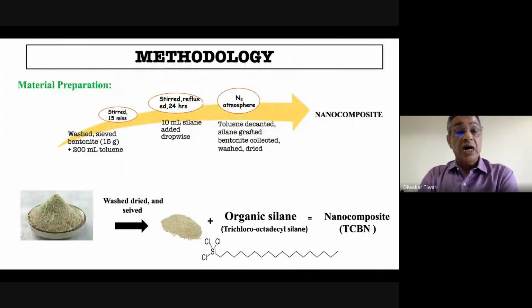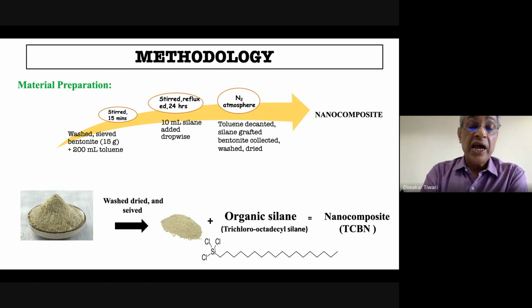Now I will come to the other part, that is the detection of arsenic, by using a slightly different material. Here we have introduced bentonite, but the bentonite is grafted with a silane, a specific silane, the trichlorooctadecyl silane, whose structure has been given here. We have grafted it and we could get the nanocomposite material. And then we have decorated this nanocomposite with silver and gold nanoparticles.